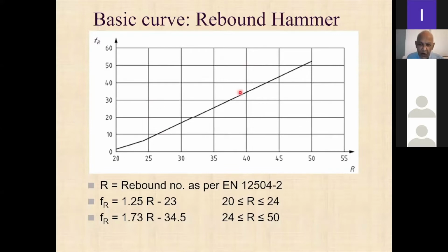We cannot draw a straight line just using these points, right? You might think that we get a set of points here and we just draw a straight line through that. No, you cannot do that. The code forces you to maintain this slope, the shape. That is the idea behind the correlation between these indirect tests and the strength. Your age and your carbonation and all of those factors will be different. That's why it's encouraging you to do this correlation. But this shape is only shifted vertically by a set amount. This slope remains constant. This slope also remains constant, right?